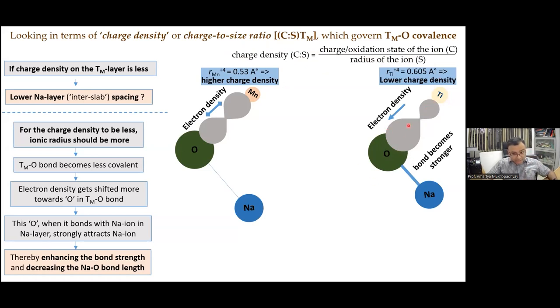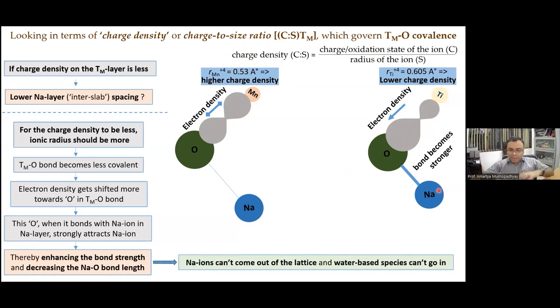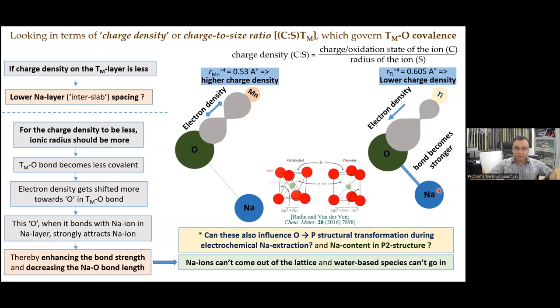my oxygen will have a greater effective negative charge and my sodium oxygen bond can be stronger. If that is the case, then my spontaneous sodium extraction upon exposure to moisture will be suppressed. And if I can suppress the spontaneous sodium extraction, I can improve the air-water stability. Can we do that? We will see from the next slide onward.